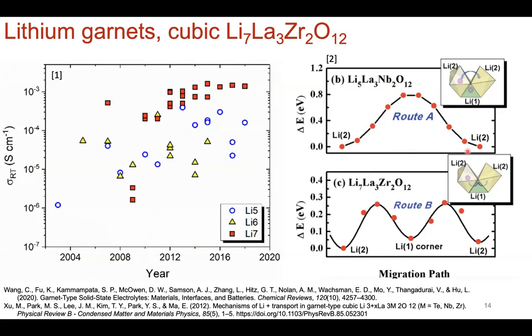But as you increase the lithium ion concentration, you modulate it so that it's not just a one-step type path, but it actually has this saddle signature pathway where the activation energy is brought down, going from octahedral face sharing with a tetrahedral site, and then going on to the octahedral site. So it's not as big of a jump. It's multiple steps, but each step is lower in activation energy. Okay. So in terms of materials design, the zirconates, stuffing the unit cell will bring down the activation energy.